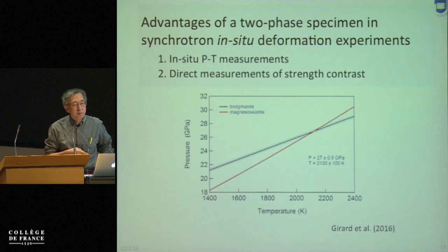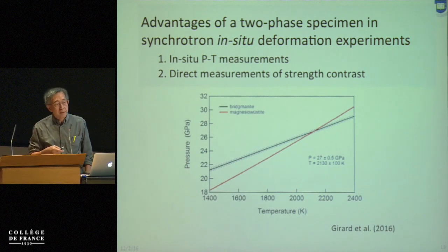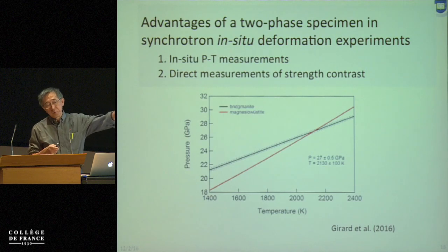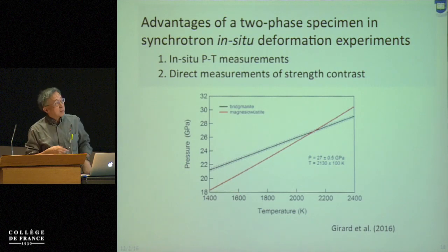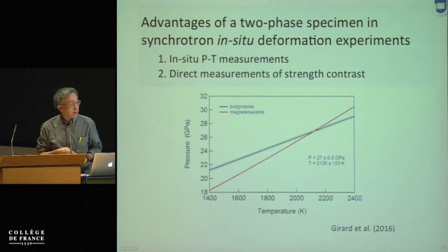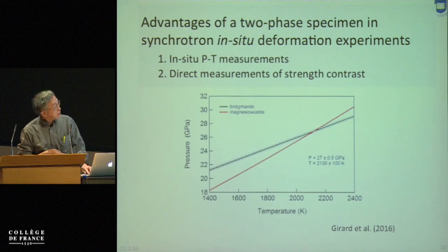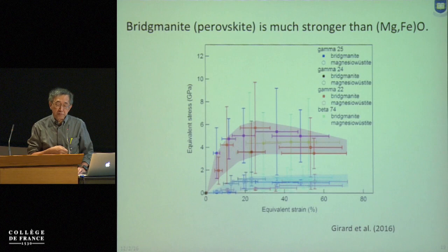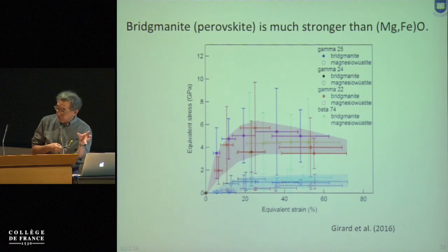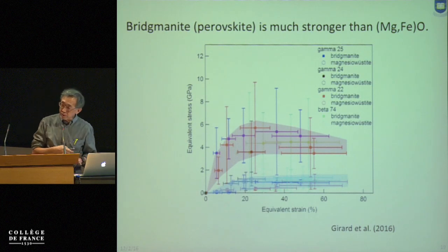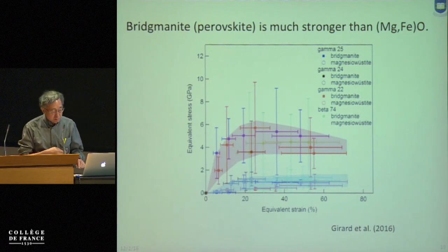And then, as I mentioned to you earlier, if you have two minerals, you have two volumes, okay? So by measuring volume, you can explain this volume by a combination of certain temperature and pressure, one line. If you have two minerals, you have another volume data, so the experimental observation must satisfy another line. So by imposing that both conditions must be met, you can determine the pressure and temperature. In this case, the pressure was 27 GPa, and the temperature was 2100 K. And then we were able to determine strengths of each phase, namely bridgmanite and MgO. And it turns out bridgmanite is substantially stronger than MgO under those conditions.